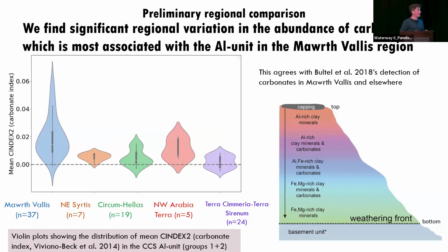Now I'm going to show some preliminary regional comparisons. So here I am showing the carbonate index, which is one of the refined spectral summary parameters. And this is a violin plot, which is basically a histogram on its side. So the y-axis is mean carbonate index across that CRISM image. And each of these different colored blobs are different regions, the 5 regions that were in the Carter et al. 2015 paper. And what we find is different distributions. Now, most do lie above 0. So most of these cubes have values consistent with some carbonate present. But interestingly, Mawrth Vallis has a different distribution to the others.